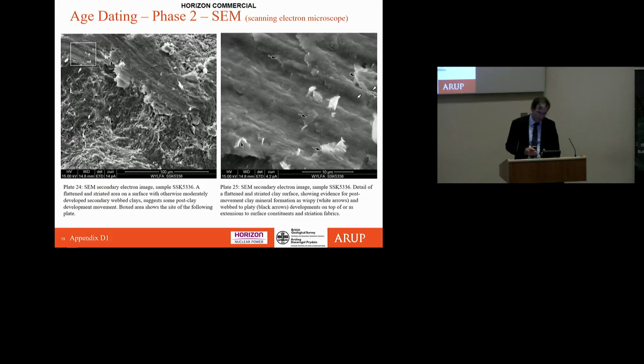And going from microscope, hand specimen, down to thin section and polished section, we're now going down to scanning electron microscope level. So we took the samples of the clay gouge to look at under the scanning electron microscope, work done by the BGS, and what they identified, as you can see in the clay gouge, were striations, telling you that movement has occurred, and many of you will be familiar with this aspect of geological faulting. You see these striations, that's an indicator of the movement, that displacement has occurred on this, and we're looking at the last phase of deformation.